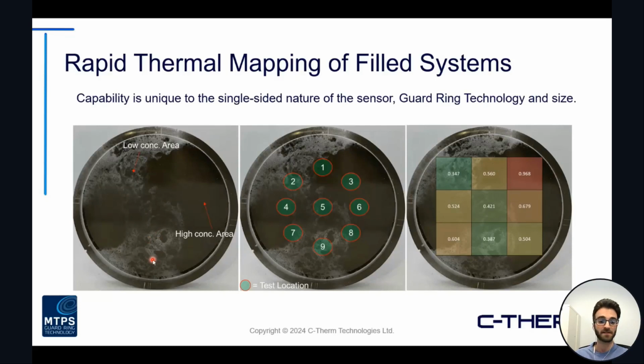But with the MTPS, because it's a relatively small active area, and again, a very quick measurement, it allows you to take the sensor, move it around at different locations on the sample, and really collect these spot measurements to do this type of mapping of the material. And then what we can do is, of course, correlate the resulting thermal conductivity values to things like the filler concentration, the internal structures, different defects that might be present, anything that's going to cause non-uniformity within the sample itself.